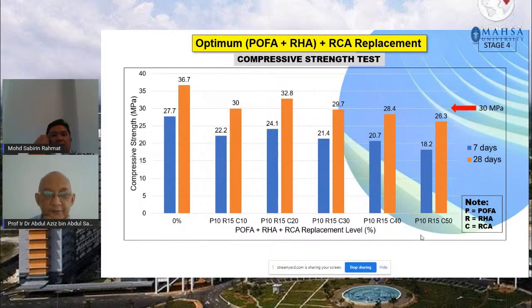Okay, now we proceed to stage 4. We have found out the optimum combination of POFA and RHA, which is 10 and 15% respectively, and now we want to add RCA replacement in the study. This is the stage 4 study. So we are going to add RCA, as you can see from this table, the C is the RCA, at 10%, 20%, 30, 40, and 50% of RCA replacement in this concrete mix. And the POFA and the rice-husk ash are maintained at 10 and 15%.